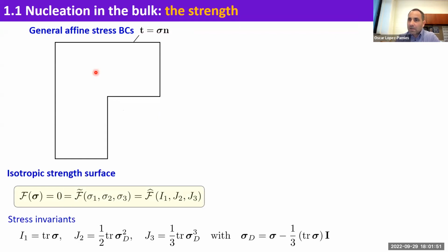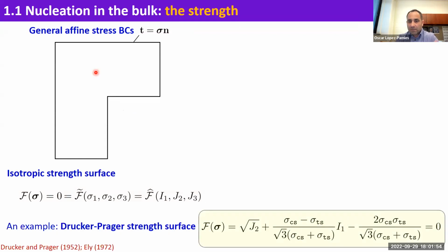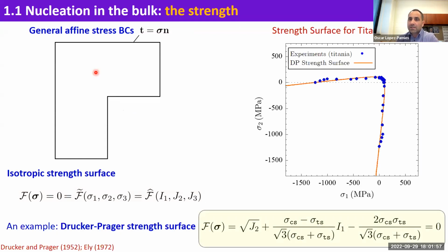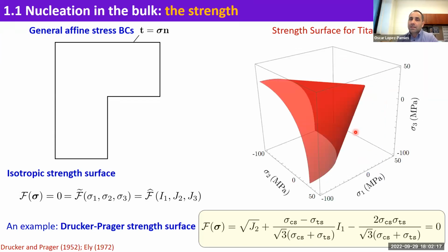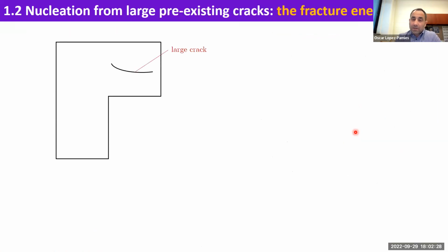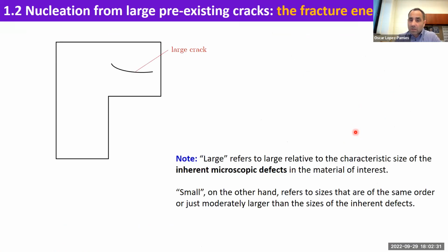And people have done experiments, especially in ceramics in the 70s. And I'm going to show you some data. This is Titania. And you can see that these are tubes that were pressurized and then extended. So the state of stress is multi-axial, and they develop cracks within the bulk at different states. So this really tells you that what you're dealing with here is a surface in a stress space. And this is just a characteristic of the material that you need to account for because this describes how fracture nucleates in the bulk.